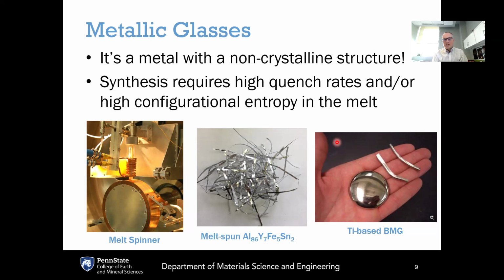Metallic glasses, just like crystalline metals, have the sea of electrons that are shared among atoms. There is an overlap between valence and conduction bands, which means that metallic glasses, just like crystalline metals, will absorb and reflect the incoming light, and therefore they are not optically transparent.